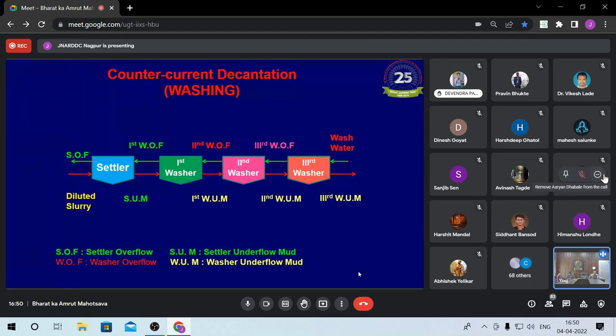Here you have the settler underflow mud which is washed. To wash the mud, you add wash water from the other end, and in an alumina refinery 6 to 7 washers are needed for reducing the concentration of the settler underflow mud from 140 GPL to around 2 to 3 GPL, which can be discharged from the system. So it is a complete chemical engineering solution which is very important for you people.